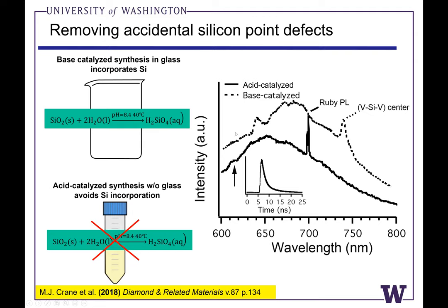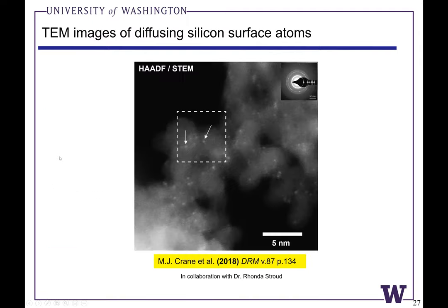We had a base catalyzed reaction that was forming the negatively charged silicon split vacancy center in diamond. And by simply switching to a plastic tube, we were able to completely eliminate that silicon split vacancy emission from the sample. And so we published this a few years ago in Diamond and Related Materials, just showing that you can get rid of the silicon and eliminate it from forming, which is the first stage in controlling what you're trying to make: make sure it doesn't happen accidentally.